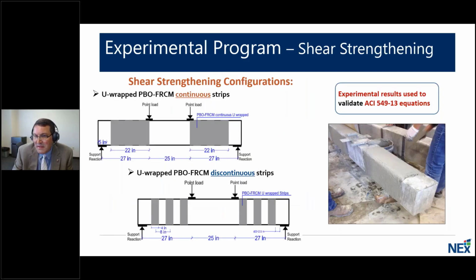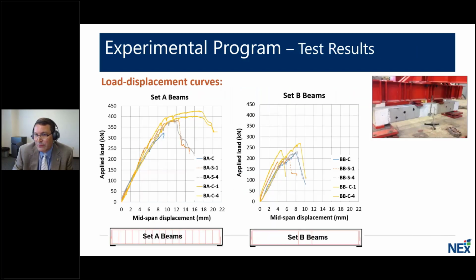In this work, a shear span to depth ratio a/d of 2.5 was selected. No strengthening naturally was applied between the points of loading, where no shear load exists. In terms of the beam, self-weight is the only shear load in the middle of the 4-point load testing. So there you can see the configuration. And again, set A is the beams with internal stirrups, and set B, as I'll show you in the next slide, are the beams without internal stirrups.